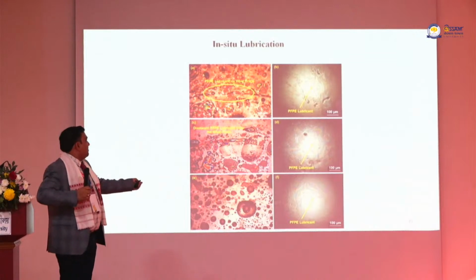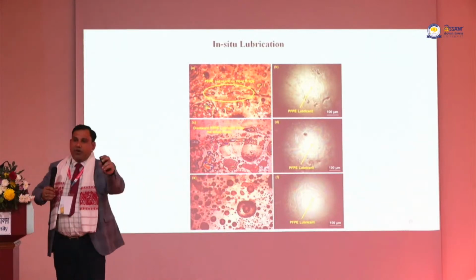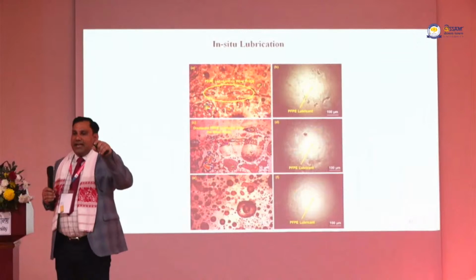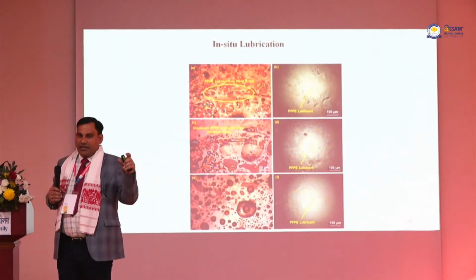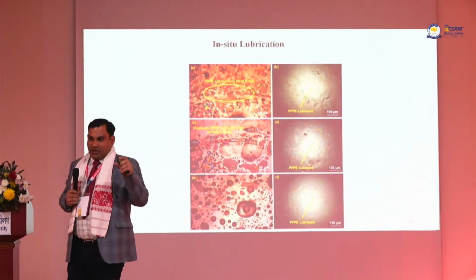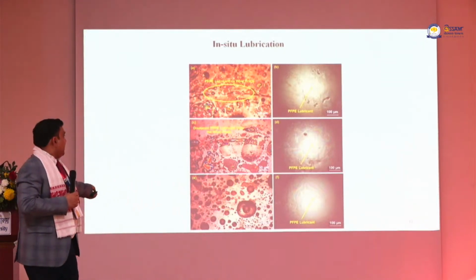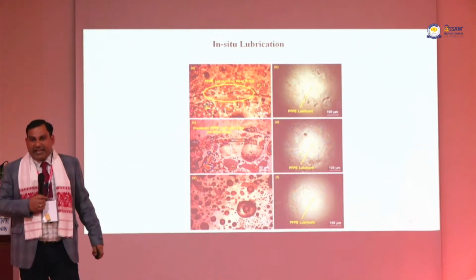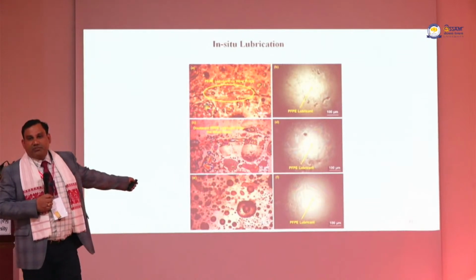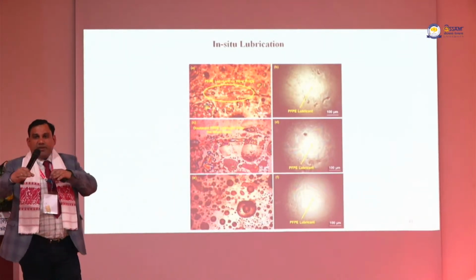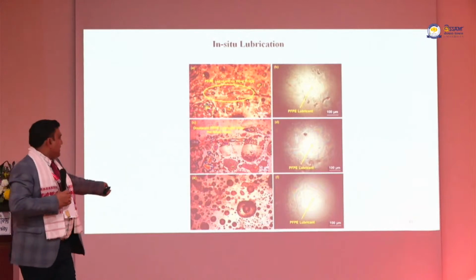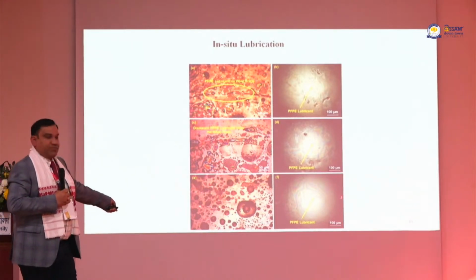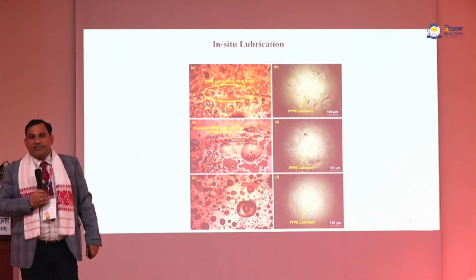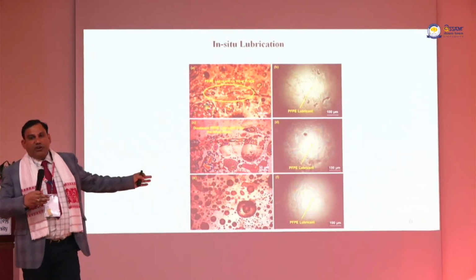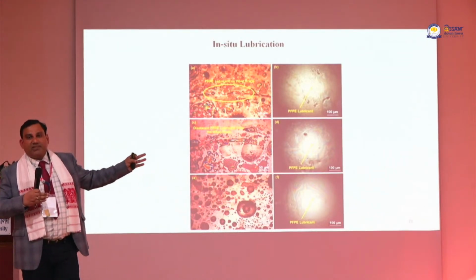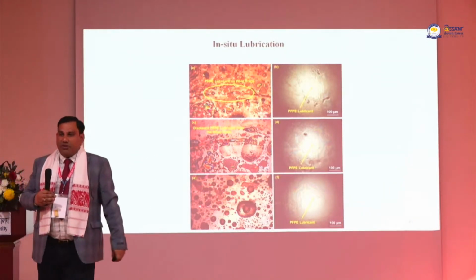Here I have developed a polymer coating, in which I added some weight percentage of perfluoropolyether lubricant. You can clearly see that after 4 lakh cycles, there is no displacement of the material, only the top layer of the lubricant is displaced. These are the samples. You can clearly see the lubricant film perfectly there at the interface. After 4 lakh cycles running continuously for 24 hours, the samples did not fail.